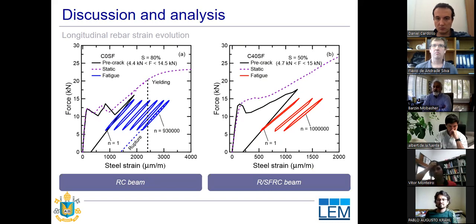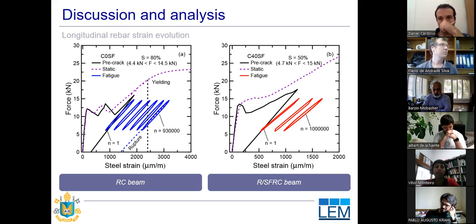So we have some of the first results. We can analyze in the first graph how the steel rebar strains are evolving for concrete without the use of fibers. And in the next graph, we have the reinforced concrete with fibers. It's possible to verify a major evolution in the rebar strains, especially without the addition of fibers.